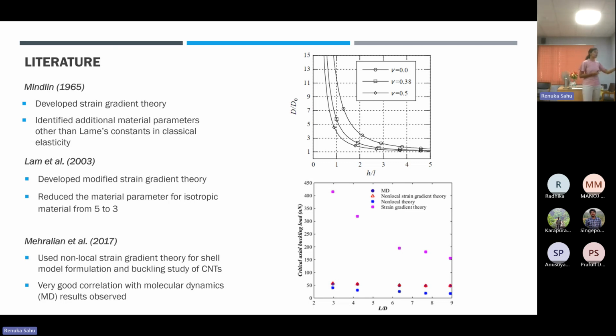Again, non-local strain gradient theory for shell formulations has been used for studying buckling of CNTs, and he was able to get very good correlation with the molecular dynamic study. It shows the importance of how the non-classical approach can correlate to the molecular dynamics results as well.